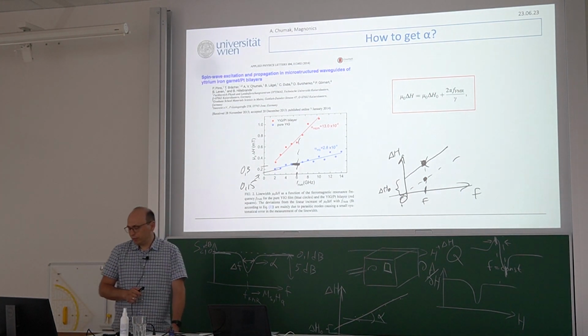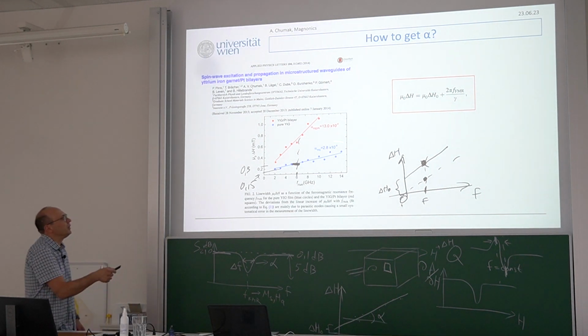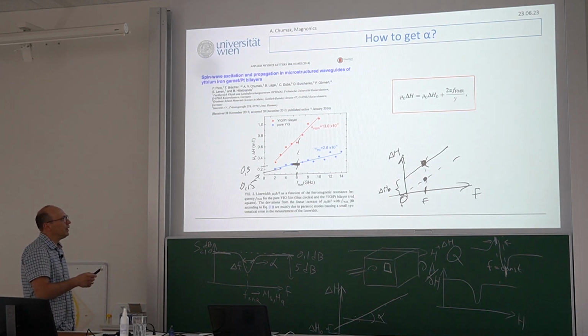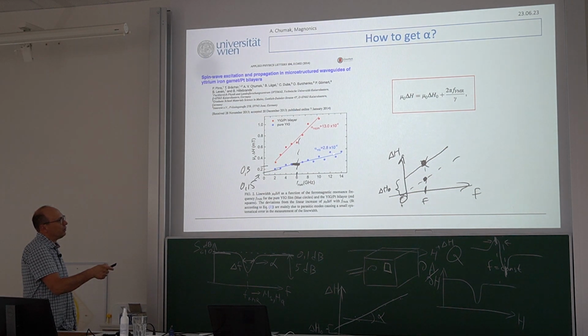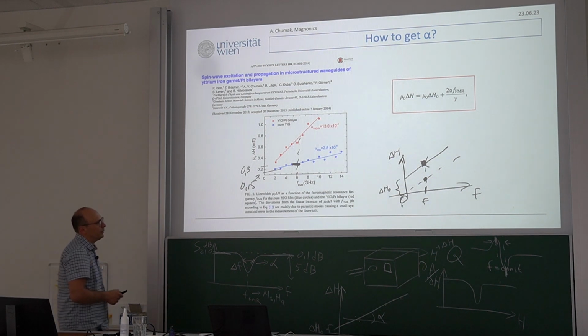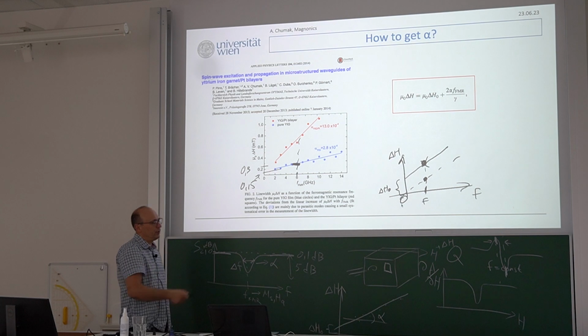It was his first attempt, but the quality was already much better than we planned. And you see that's how the picture looks. It really is this delta H already recalculated. When you plot it as a function of ferromagnetic resonance frequency, it's really a line, and it goes to some value around 0.5. So delta H0 was not 0.